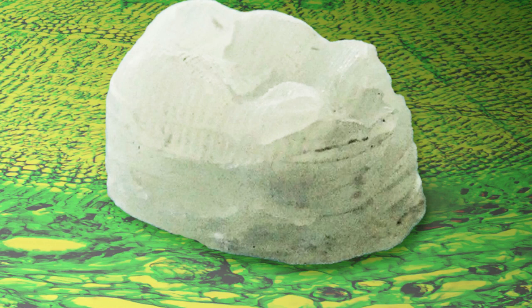They tested the material's resistance to cracks using tools to insert first nano and then micro scale cracks. They found that across multiple scales, the composite's arrangement of cellulose grains prevented the cracks from splitting the material. This resistance to plastic deformation gives the composite a hardness and stiffness at the boundary between conventional plastics and metals. Going forward, the team is looking for ways to minimize the shrinkage of gels as they dry. While shrinkage isn't much of a problem when printing small objects, anything bigger could buckle or crack as the composite dries.